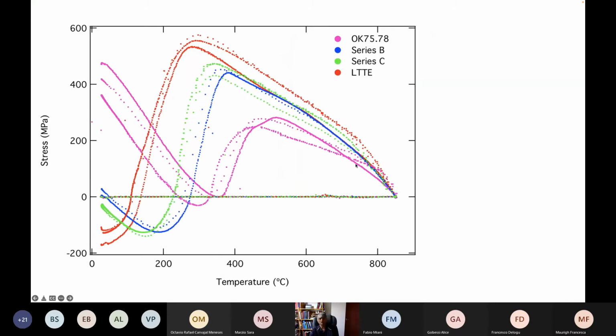So first of all, this is our control electrode, which transforms at a high temperature. And you can see that you're left with a large level of residual stress in the specimen by the time it reaches ambient temperature, because the transformation is exhausted at this point. For all the other alloys, where the transformation temperature is of the order of 200 degrees centigrade or lower, we end up with almost zero stress or even a compressive stress at room temperature.